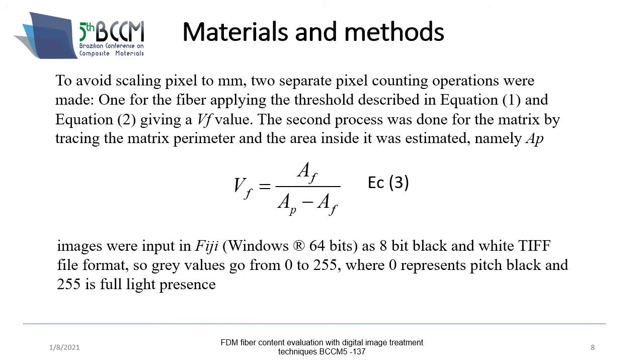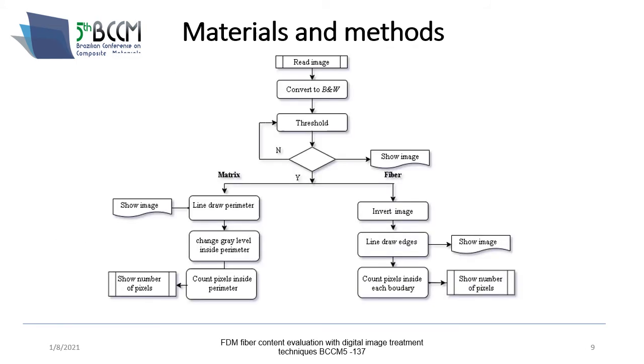We use the image in Fiji software in an 8-bit black and white TIFF file format. This flow diagram represents the segmentation process. First, we read the image, then convert it to grayscale and black and white, then apply the corresponding threshold to separate the fiber and matrix regions. So we first draw the perimeter of the matrix and calculate the overall area, and for the fiber we draw line edges to show the amount of fibers. Then we count the pixels inside each of the boundaries and determine the area of the fibers.